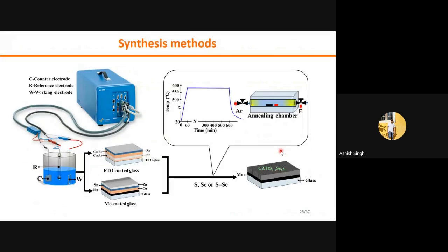For the fabrication of CZTS, we were using the potentiostatic electrodeposition process, and we used two types of conducting substrate, FTO and Mo coated glass. On FTO coated glass, we deposited copper, tin, copper, and zinc metal precursors by the electrodeposition method. Similarly, on moly coated glass, we deposited copper, tin, and zinc layers. These precursors were annealed in a sulfur, selenium, or sulfur plus selenium atmosphere to make the compound semiconductor. This is the technique we use for the sulfurization.